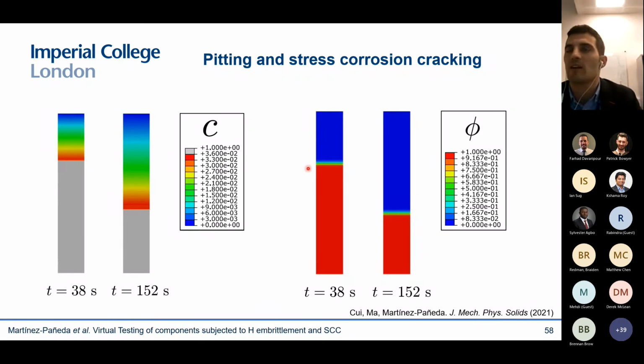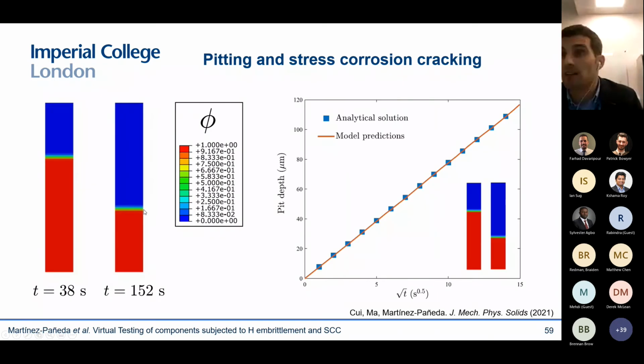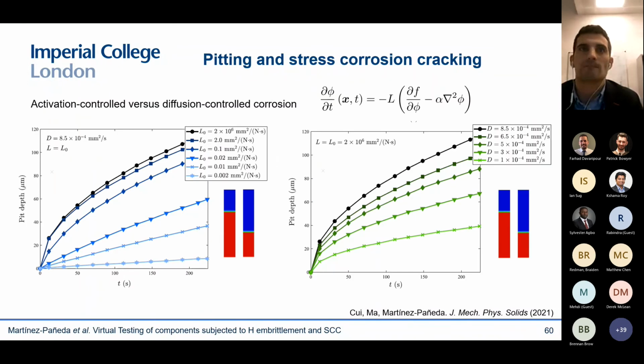This is with Abaqus. You can see that the corrosion front is growing as a function of time. And this is the distribution of the metal ions away from the crack. So you go from 0 all the way to the saturation concentration. And as I said, there are some analytical results, and you can see that the model reaches a very good agreement with those analytical results.